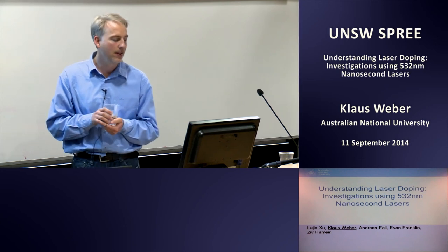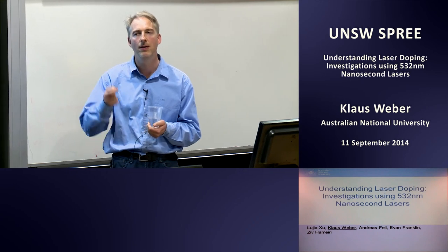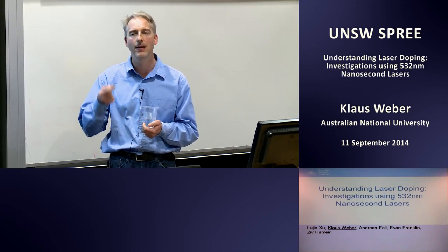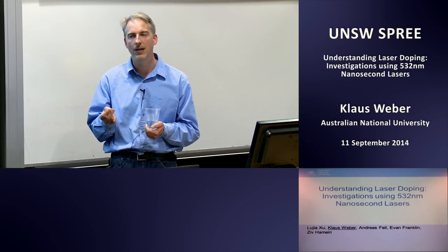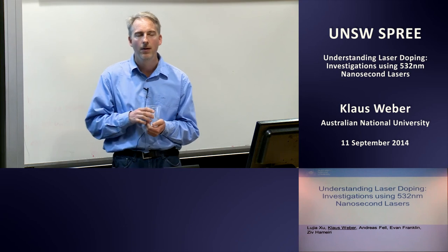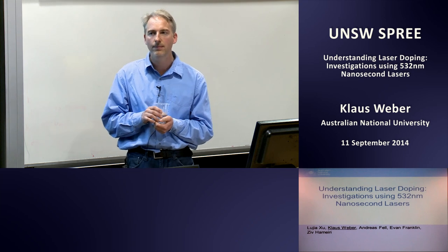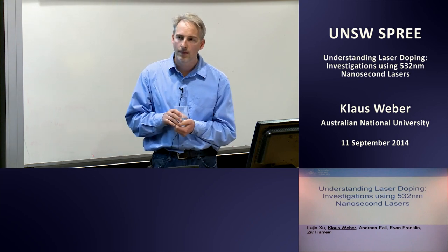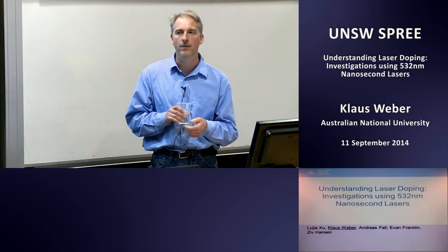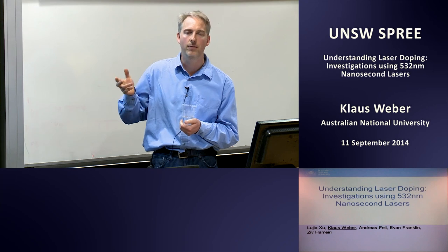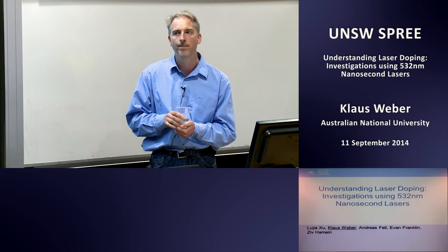One of the things that we could see sometimes with the silicon nitride in the SEM images is there seem to be some little particles in the melted region. So we think that maybe there are some precipitates or something like that. But we can't rule out that it's mainly due to thermal stress as well. Is the silicon nitride PECVD or low pressure? This was mainly PECVD. I think they were all PECVD films. I only showed one, but we used several different recipes and several different refractive indices.